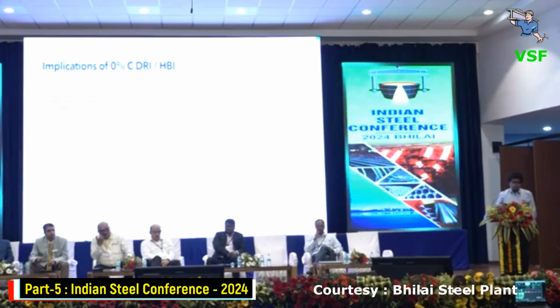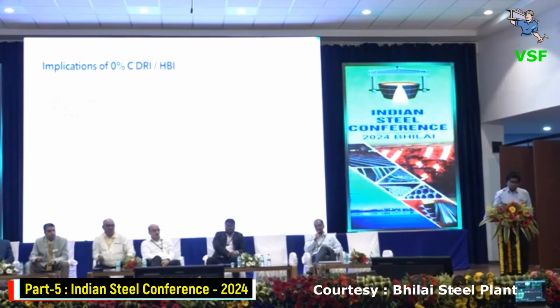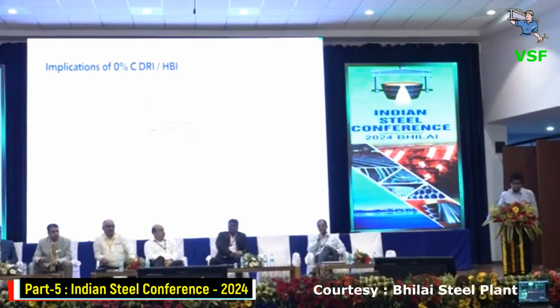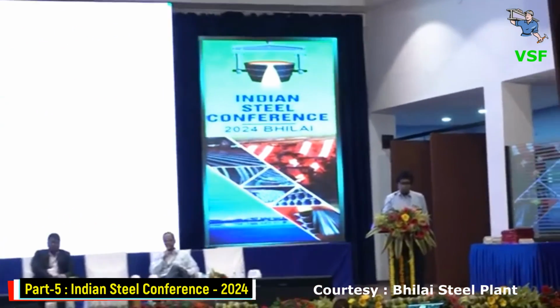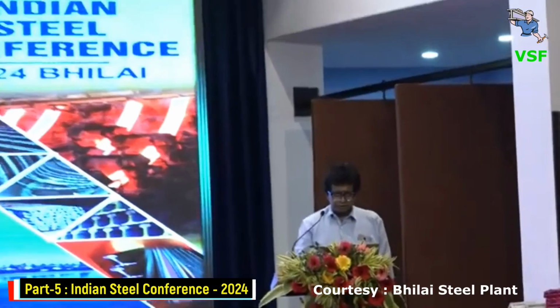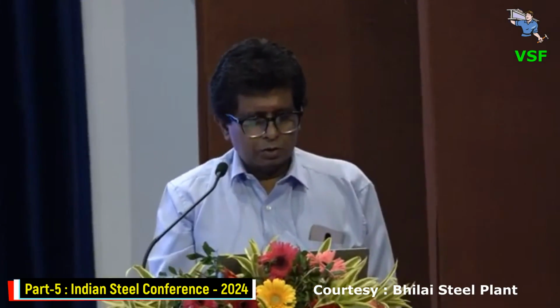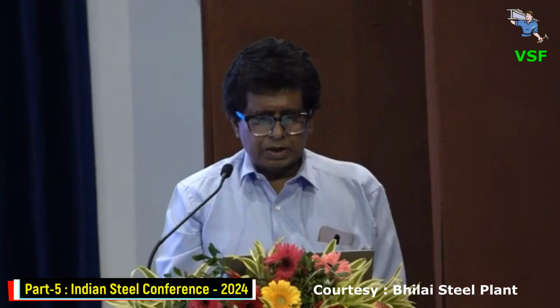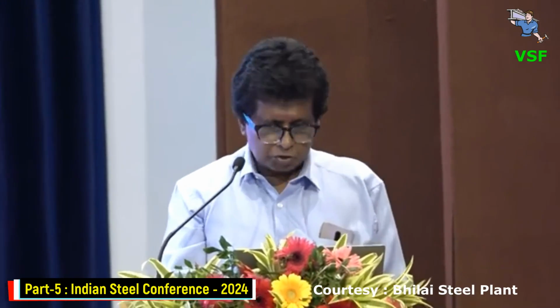So what is the implication of using 0% carbon DRI or HBI? Primarily, most importantly, you will be requiring more energy, because the temperature at which the steel melts increases with decreasing percentage carbon. This temperature will increase definitely. And thermodynamically speaking, when you talk about low carbon steel, you normally produce more FeO in the slag, that calls for lower yields. And also there will be less available in situ chemical energy in the DRI because of almost no carbon.